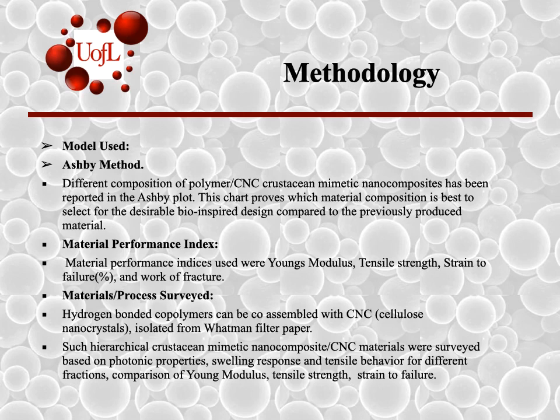The materials or process surveyed was that hydrogen-bonded copolymers can be co-assembled with CNC, which is isolated from Whatman filter paper. Such hierarchical nacre-mimetic nanocomposite materials are surveyed based on photonic properties, swelling response, and tensile behavior for different fractions, with comparison of Young's modulus, tensile strength, strain to failure, etc.